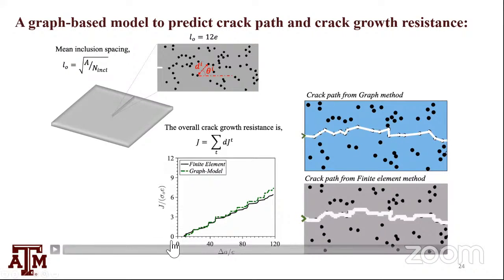Now, one trick here, I'm not plotting the initiation value. I'm assuming my crack growth has begun. I'm just focusing on crack growth resistance, not the crack growth initiation resistance. So J1C is subtracted. We'll come back to that challenge later.